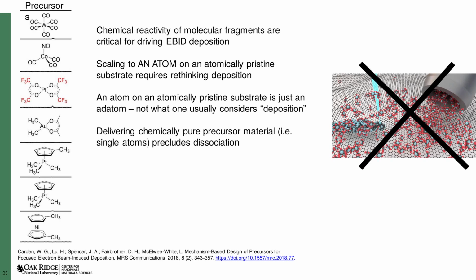But even if we ignore the fact that we do not have a clear picture of what deposition should look like at the scale of an atom, we have another problem. If we supply a chemically pure precursor material, single atoms, to the sample, there is nothing to dissociate. The mechanism that e-beam is using to drive deposition requires molecular precursors, not atomic precursors. So the e-beam approach to deposition cannot physically scale down to single atoms. On the face of it, it seems like a rather hopelessly intractable problem.